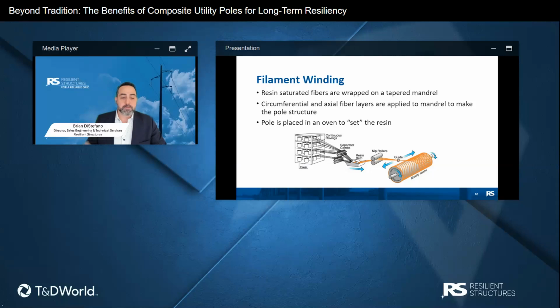These final circumferential layers are applied with a very high resin content, higher than the resin content of the structure beneath. That results in a very resin-rich surface that boosts the finished product's durability and significantly enhances its UV resistance of the entire structure.